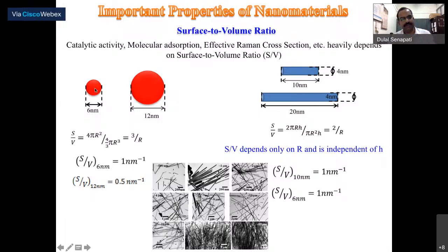So think about a 6 nanometer particle where the surface to volume ratio is 1 nanometer inverse. But the same material, a 12 nanometer particle, has a surface to volume ratio of 0.5 nanometer inverse. So that means for the bigger particle, the relative surface area exposed per unit volume is reduced by half. So this particle is not as active as the small particle.